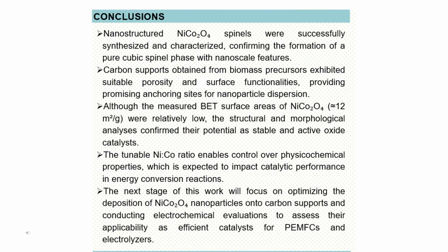With the preliminary results, we conclude that the nanoparticles show nanostructured spinels of nickel cobalt. They were successfully synthesized and characterized. These show the formation of a spinel phase with nanoscale features. Carbon supports obtained from biomass precursors show porosity and surface functionalities. This provides a promising anchoring site for nanoparticle dispersion. The surface area of the spinel was relatively low.